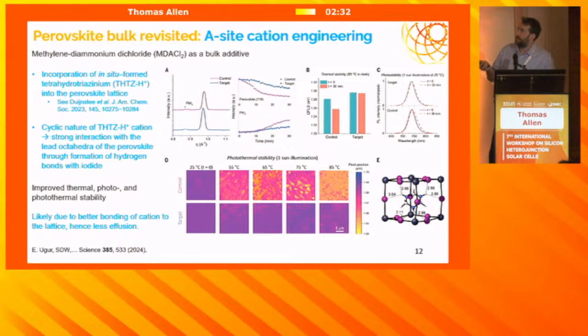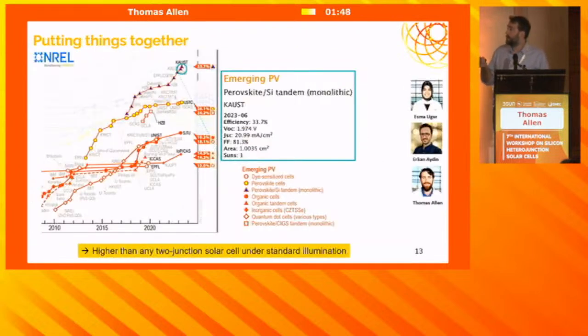We showed in our triple cation mixed halide perovskite that this is also being formed. And we believe that this THTZ molecule, because of its shape, its cyclic nature, means that it's able to more strongly bond to the halides in the perovskite, and it's able to bond to more of them. And even with a very slight concentration that we're adding in our film, it confers photostability, thermal stability, and photothermal stability to the perovskite, and increases the radiative efficiency of the perovskite, as I'll show, from about 0.4% to 1.4%. So that's a huge increase in voltage. And with that, we were able to make the 33.7% cell. So the difference between what I'll show soon, between the 32.5% cell and the 33.7% cell, is the MDACl additive in the bulk.